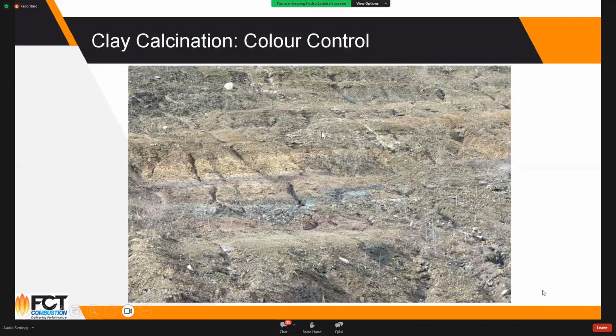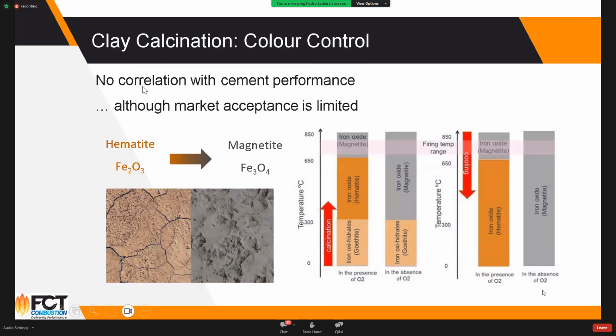So what we know, it's always the first question whenever you're talking about clay, what about the color? Clays can have different colors originally. After they are activated, they can become red, or the cement can become pink. We know this pinkness has no correlation with cement performance, although the market acceptance for pink cement or red hue cement is really limited. So we must try and control the hematite and try to get as much magnetite and prevent the iron from being reported in this more oxidized form. So different ways of doing that, but basically what is being done lately is to control the atmosphere inside the kiln and during the cooling.